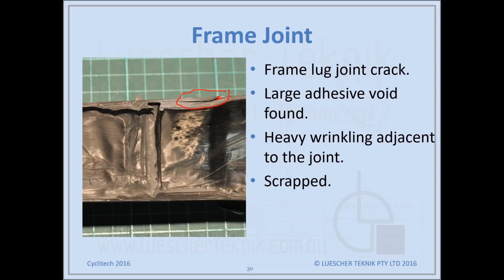The other thing of real concern we found was this area of wrinkling adjacent to that junction. This is the down tube to head tube junction, so it's a very, very high stress area on the bike, and you can see also some porosity in this area through here. There was a whole bunch of areas that are structurally compromised. So this bike was scrapped.